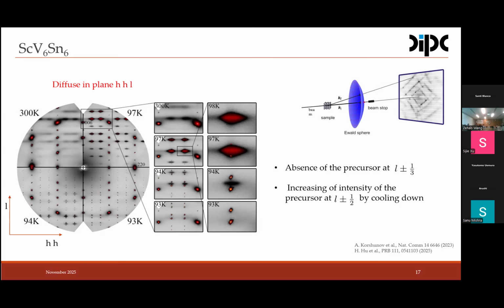If we look at the diffuse signal along the L direction, we see how the intensity increases with L, which essentially tells us that we are dealing with diffuse scattering coming from the condensation of a soft mode. If it were related to disorder or occupational substitutional disorder, the diffuse scattering should decrease with momentum. On the other hand, we can also distinguish how the intensity changes from high, low, high, low, high, low. This is telling us that the soft mode is a consequence of the out-of-phase vibration of some atom which displaces along the Z direction.